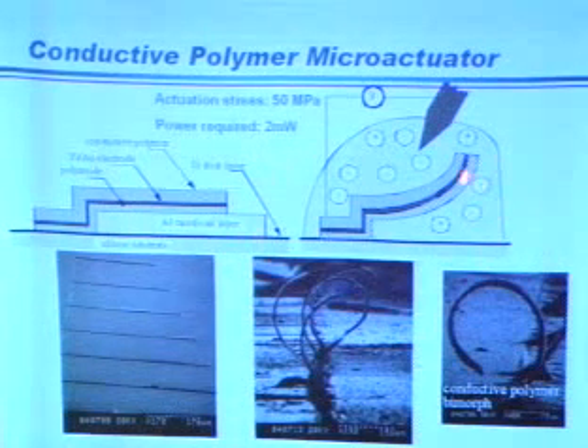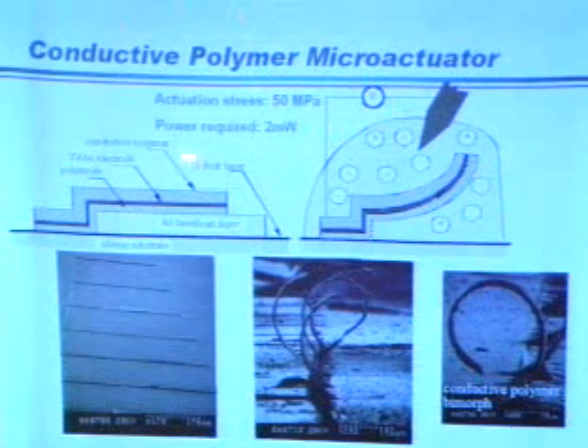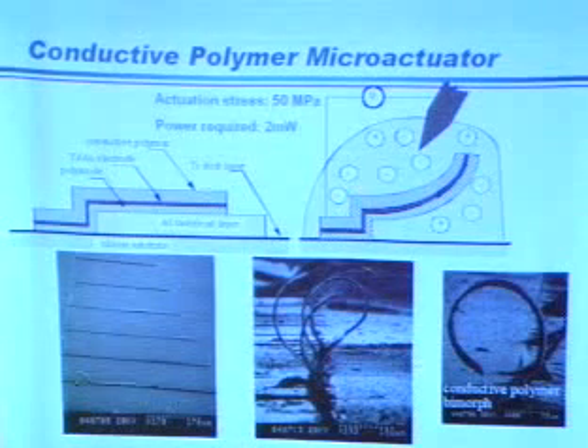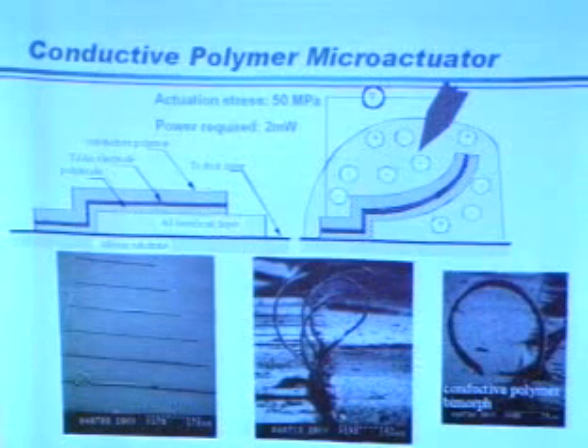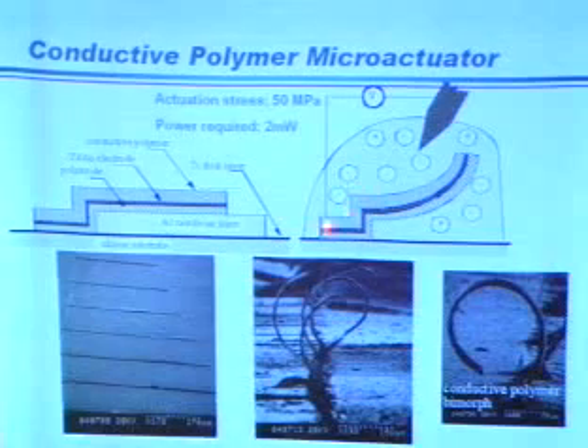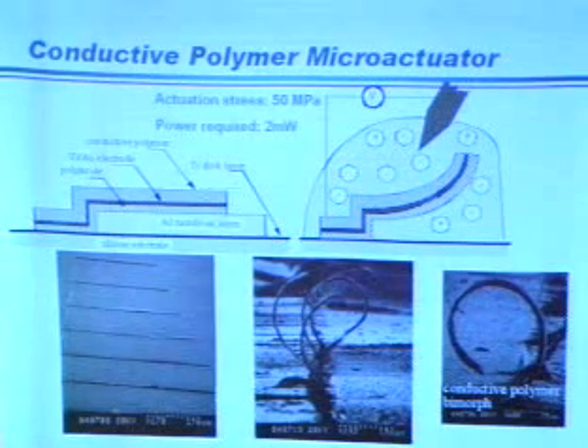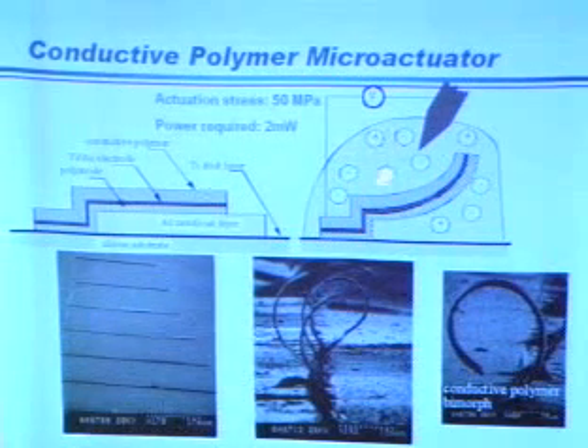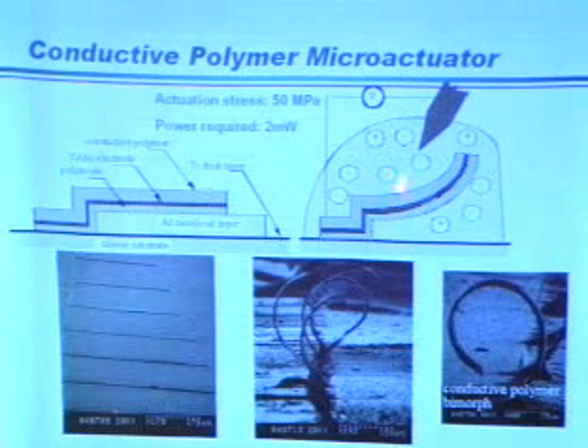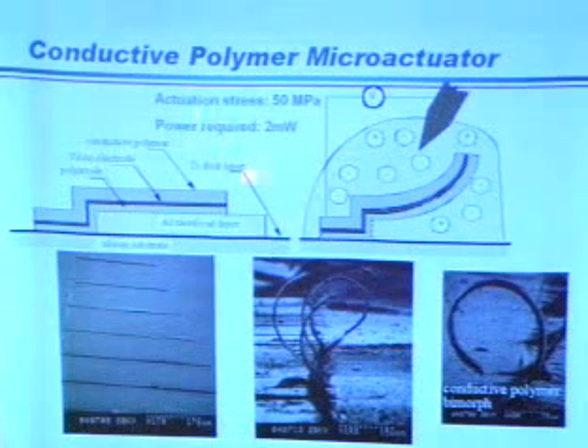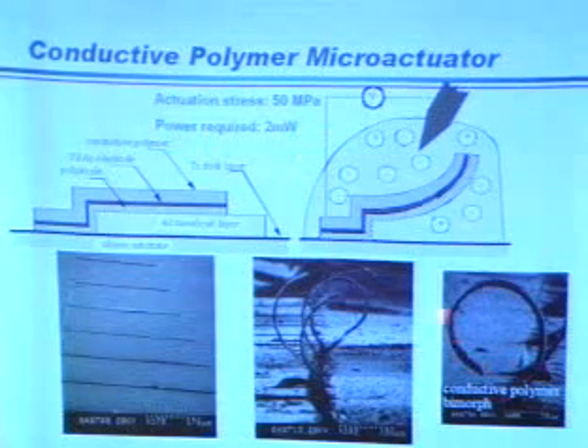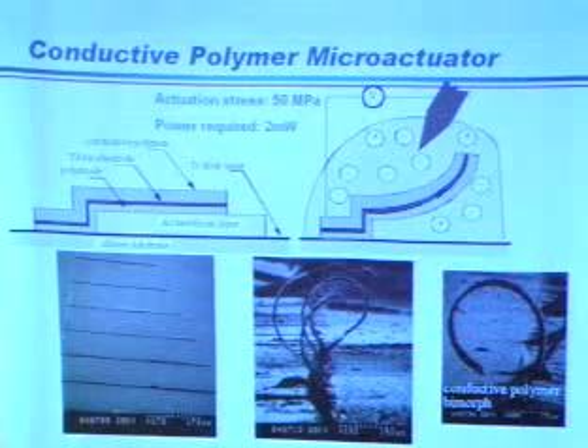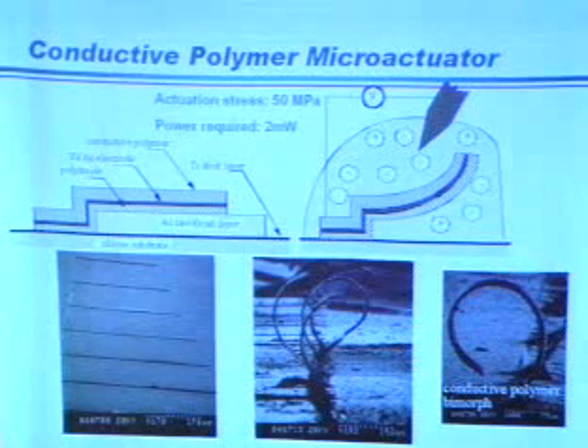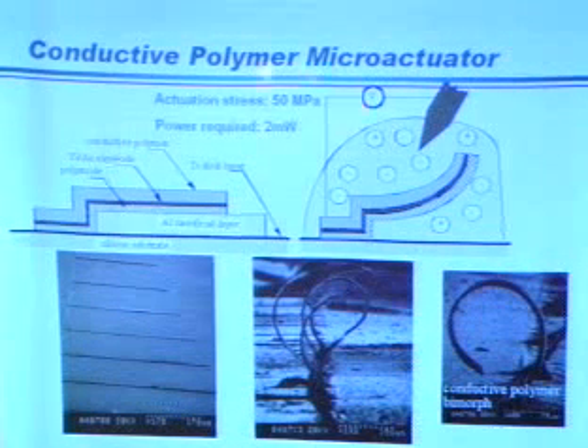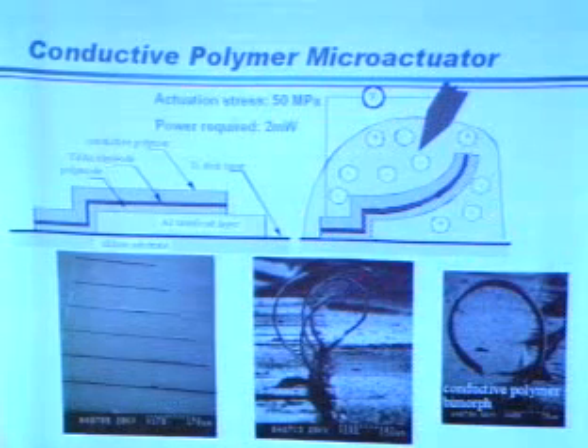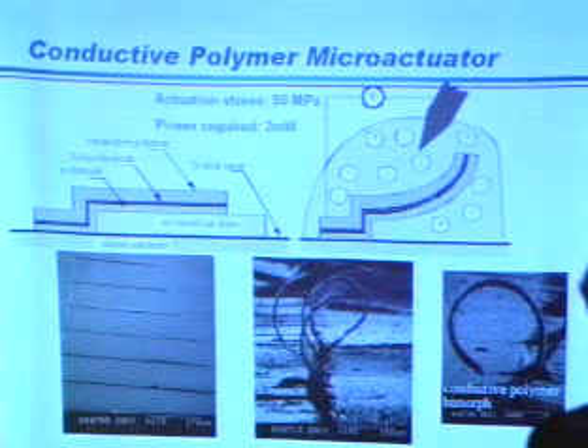Another way to use this thermal bimorph is using different materials. In this case, mimicking muscle motion, we use conductive polymers. The way it works is basically the polymer backbones will be doped with certain kinds of ions, and these ions can be driven in and out with a voltage bias. And it's really low power, 2 milliwatts. I can take this conductive polymer in a circular configuration and completely open it 360 degrees with relatively large actuation stresses. So it's another way. It's basically a chemo-mechanical actuator that could be used.